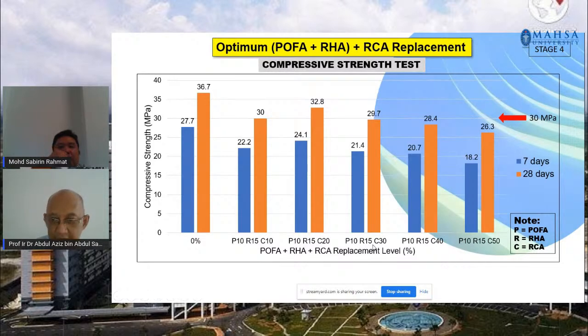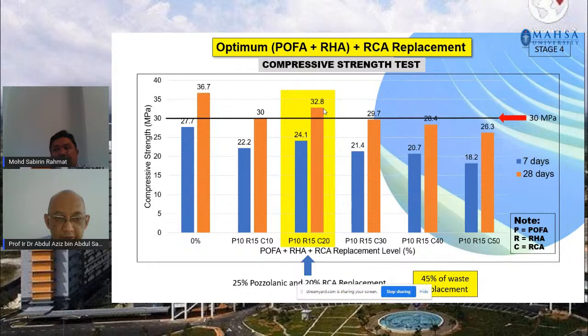Okay. So again, our target strength of concrete is 30 megapascal. From this study, at 28 days, a mix of 10 POFA, 15 rice-husk ash, and 20 recycled coarse aggregate, we achieve 32.8 megapascal. So from this particular mix, as you can see, we have 25% pozzolanic and 20% RCA. So we are talking about nearly 45% of waste replacement in this particular concrete mix. And yet, with this 45% of waste replacement, we can still achieve a concrete strength of 32.8, higher than 30 megapascal, which is our target strength. So that's stage 4, which we have achieved.